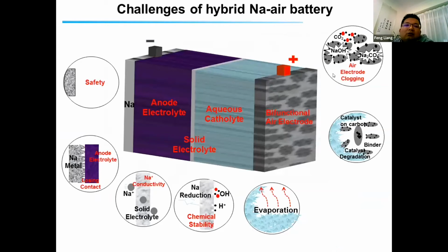Although this battery has a lot of advantages, there are a lot of challenges. As we know, there is the safety issue, because it uses sodium. It also has a problem of the contact between sodium and the anode electrolyte. Also, we should improve the ionic conductivity of the solid electrolyte. In the case of the cathode side, as we know, the aqueous electrolyte is easy to evaporate. Also, we need to develop the bifunctional catalyst for the OER and ORR, so as to reduce the overpotential.